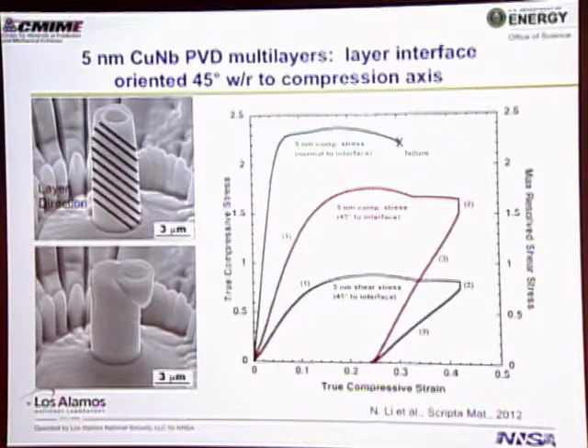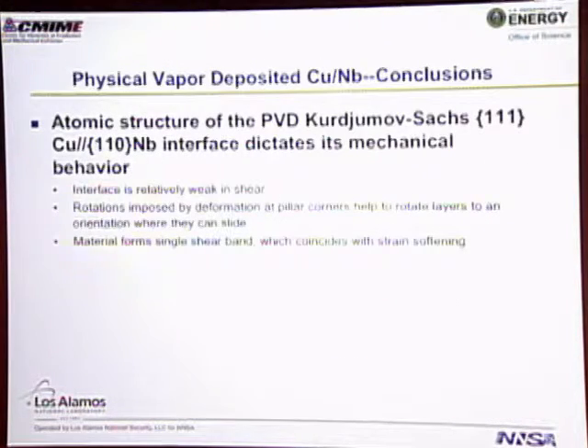We can measure strength relative, so this is the strength of this particular test. This is the strength when we compressed perpendicular to the layers. And what you find is that this material is actually much weaker in this stress state. So what we've been able to find is that the interfacial shear strength of this particular type of interface is extremely low. So what we found is that this particular structure, the interface dictates its mechanical behavior. The interface itself is weak in shear.